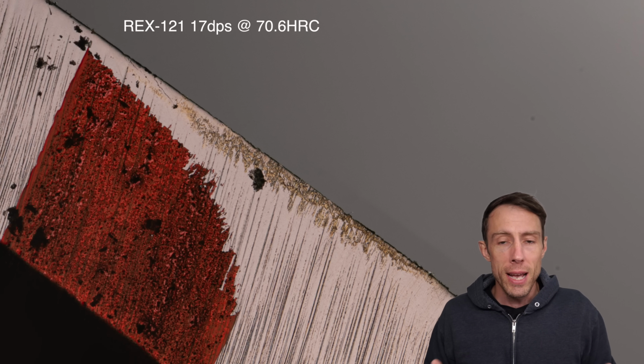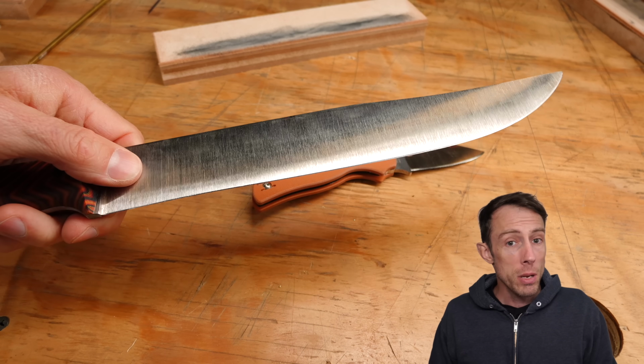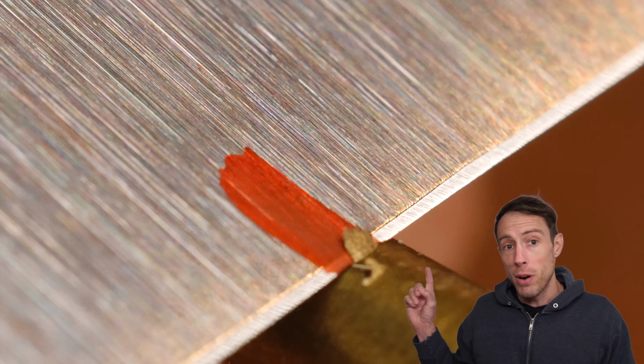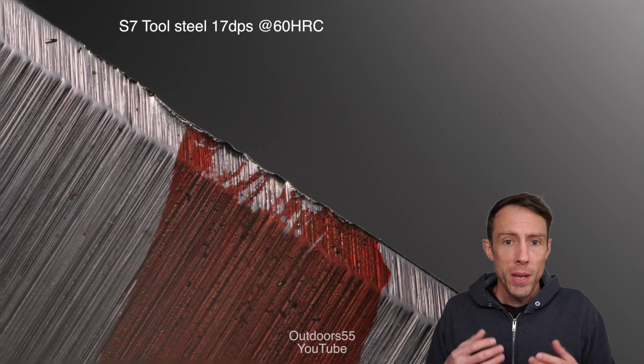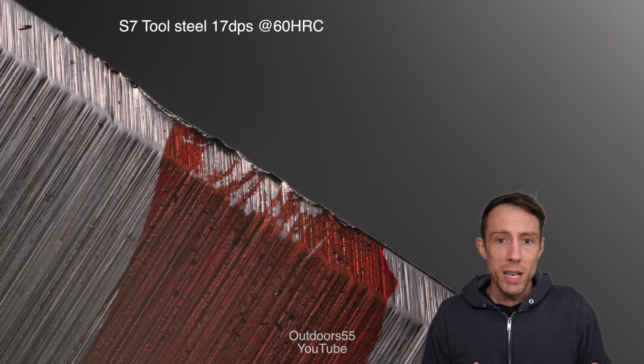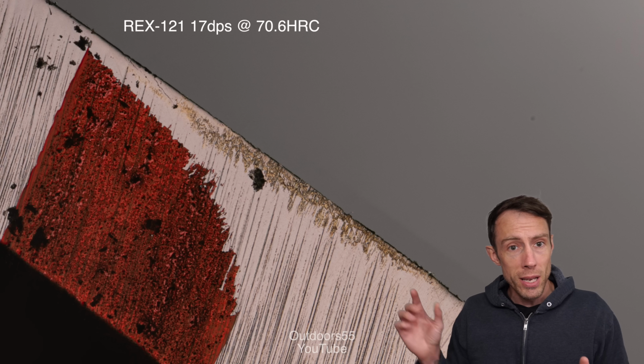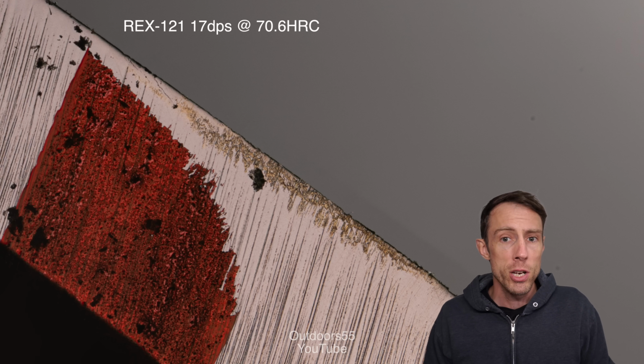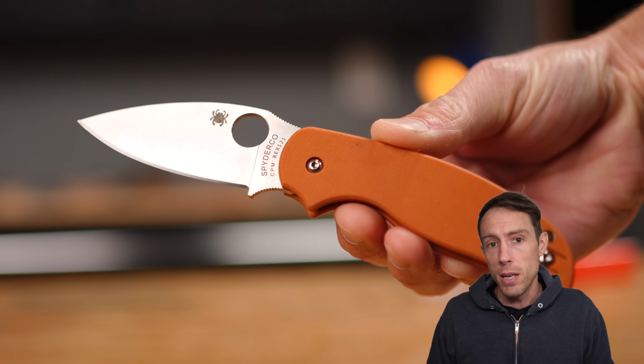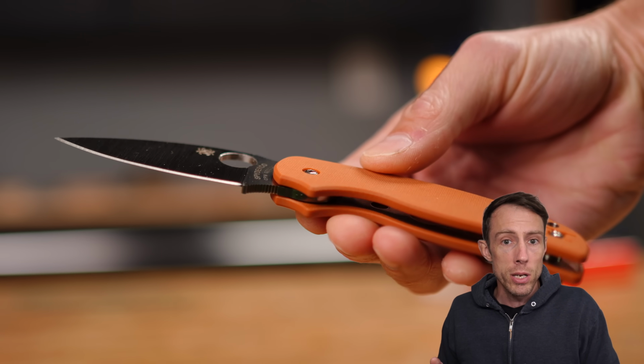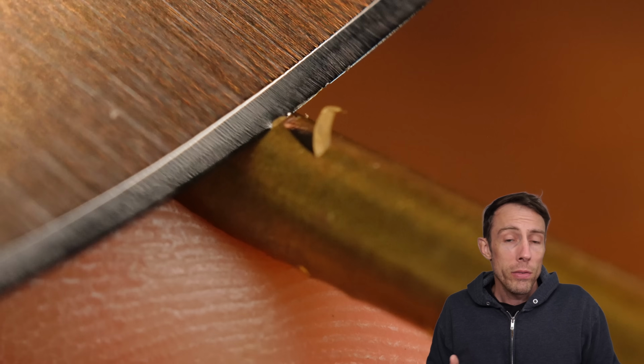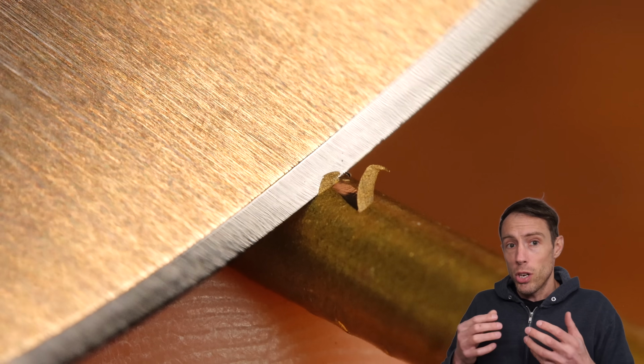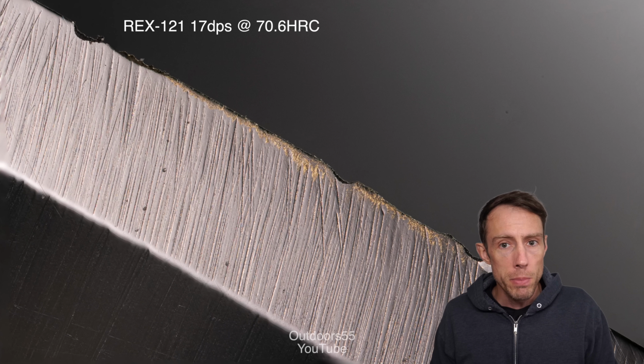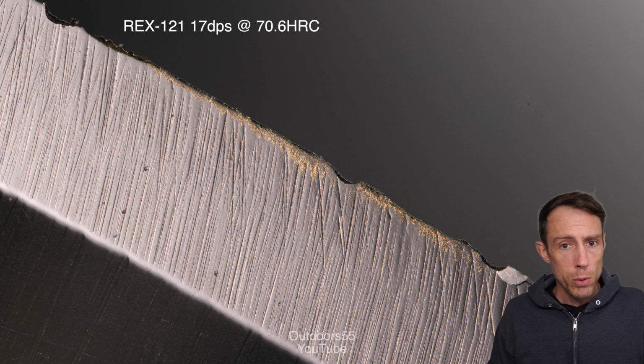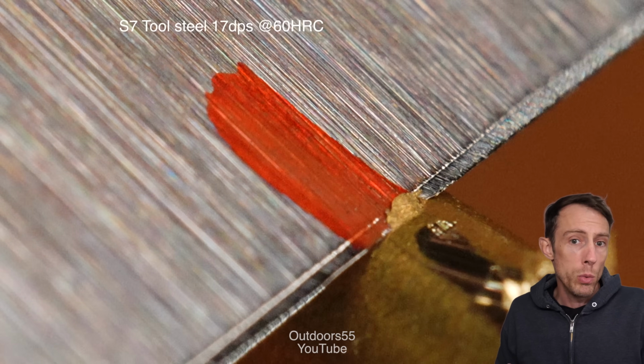Now, comparing this with a steel like S7 tool steel at 60 HRC, which is some of the world's toughest knife steel, carving the same brass rod yields much worse results. This is probably going to surprise a lot of you, but it's because the increased hardness of the Rex 121 gives the apex much more resistance to deformation, which for a lot of the stuff that you're going to use a knife of this size for, is going to be much better for edge stability. However, if we start to dig in and pry with that apex, we'll start to see more apex damage in the form of chipping. This is where that low toughness will come into play: the S7 steel with its increased toughness will bend without a crack forming, while the Rex 121 will break.